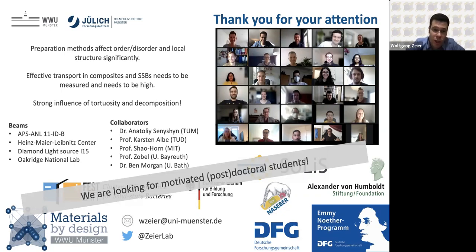And we should look at that in neutron diffraction, so we can actually figure out what happens with chloride and sulfur, or at least with lithium. That would mean making a lot of batteries to get a cubic centimeter of volume. What we have not done yet is keep them polarized for a very long time. When we run polarization experiments to measure partial electronic conductivities, after the polarization the disorder has not changed, but these measurements are performed over a few days. What happens after weeks or months, I don't know.